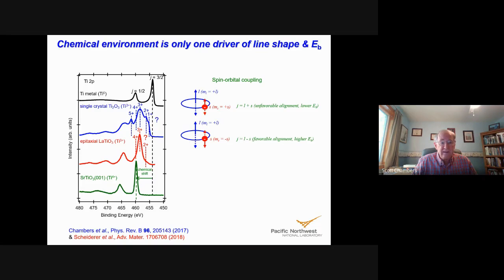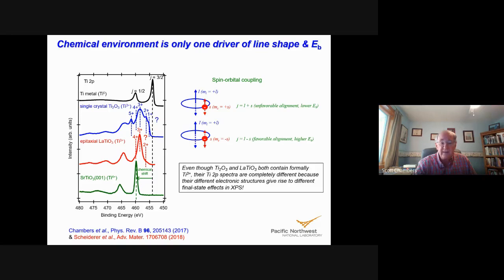And so clearly, just because the formal charge is the same does not mean the spectra are going to be the same, because these other effects kick in. In this case, we have different crystalline structures, different electronic structures, and this gives rise to different final state effects in XPS that completely change the spectra. That's why it's really essential that we understand these different effects if we're going to use XPS intelligently.